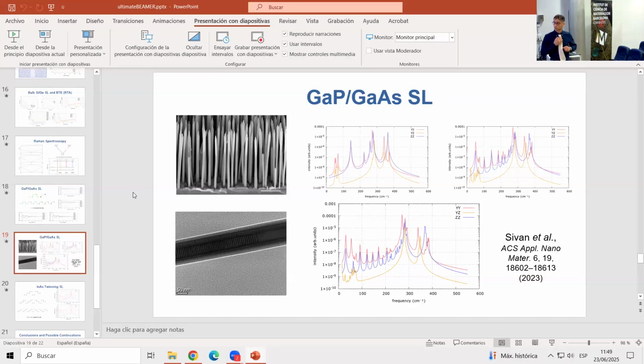So I have one last question, if I might, and it's on something that you wrote in the thesis but didn't mention today. I'm not sure I got it correctly, so I took some notes. At a certain point, when you compare the response of the compositional superlattice with the twin superlattice, you link the strength of the Raman peaks to the homogeneity of the force field, and then you use this, at least to my eyes as a reader, in support of the fact that twin boundaries are not that efficient phonon scatterers compared to compositional boundaries.